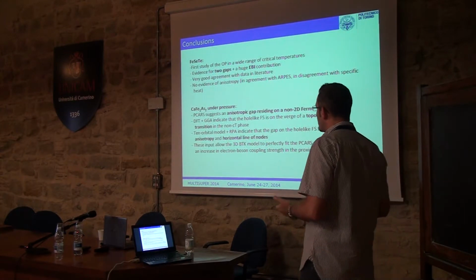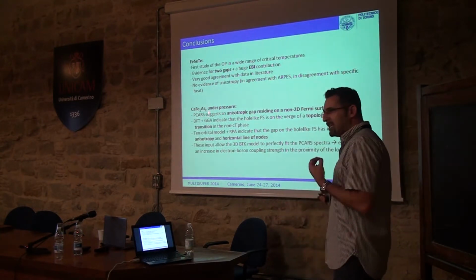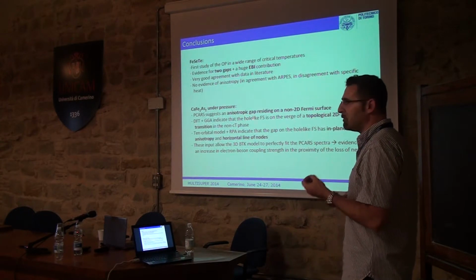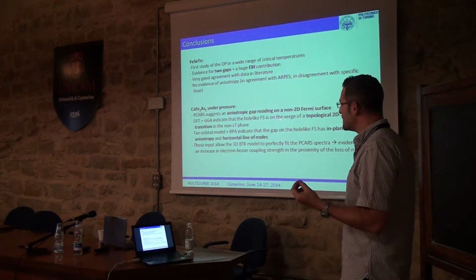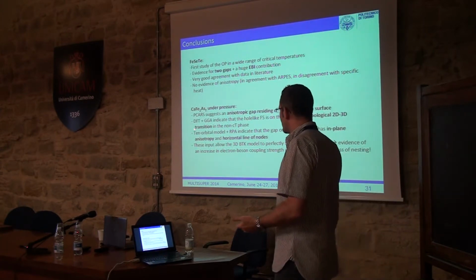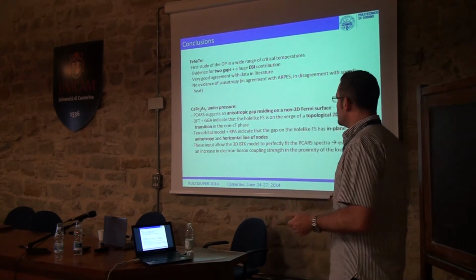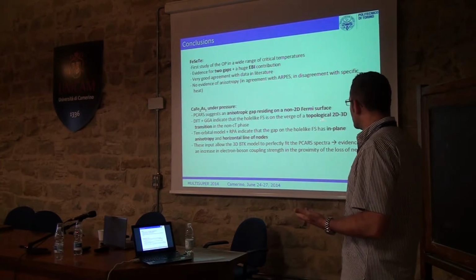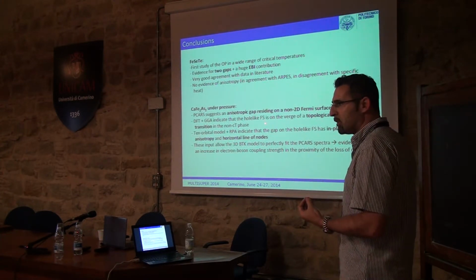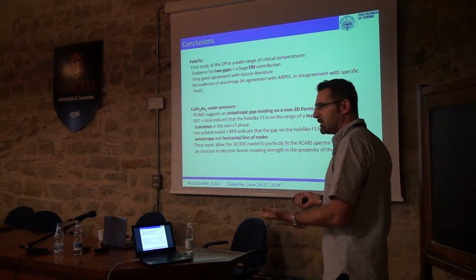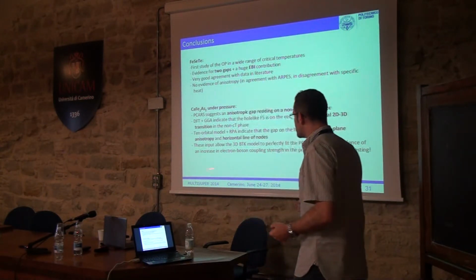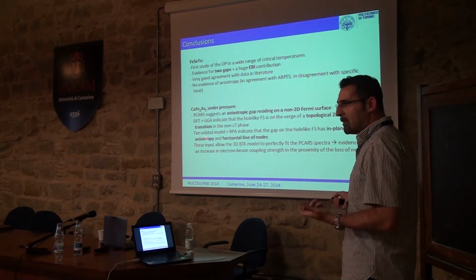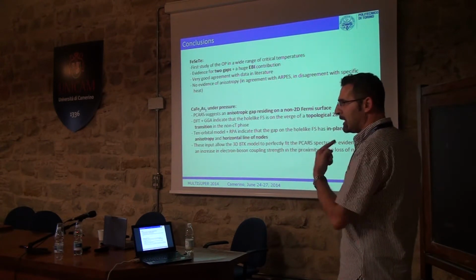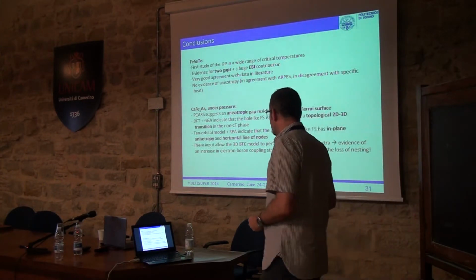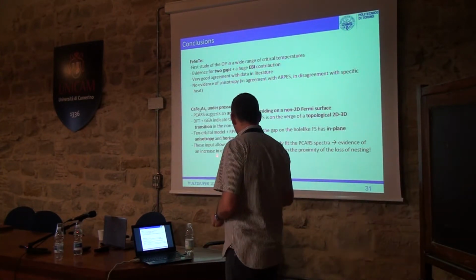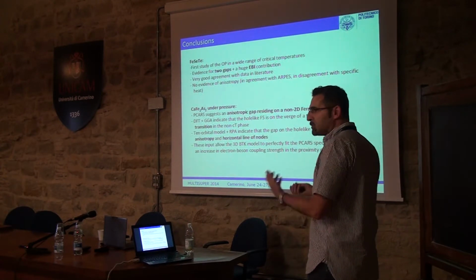For CaFe2As2 under pressure, the point contact itself alone suggests an anisotropic gap that resides on a non-2D Fermi surface. Then we have done many calculations by DFT and by an orbital model, and we have really confirmed that the Fermi surface that hosts the anisotropic gap is on the verge of a topological transition, let's say a Lifshitz transition. And the gap really has nodes, but it has an in-plane line of nodes. Sorry, a horizontal line of nodes. This information allows us to perfectly fit the curves.